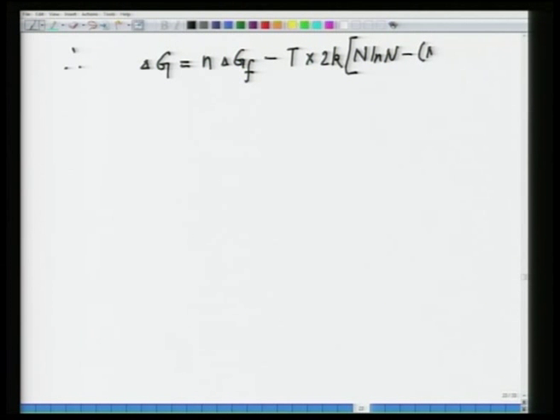So, now the net free energy change, the total free energy change that we wrote earlier, delta G, would now be equal to n delta Gf, this is the first term, minus T into 2k into [N ln N minus (N minus n) ln (N minus n) minus n ln n]. So, this is your expression for free energy.